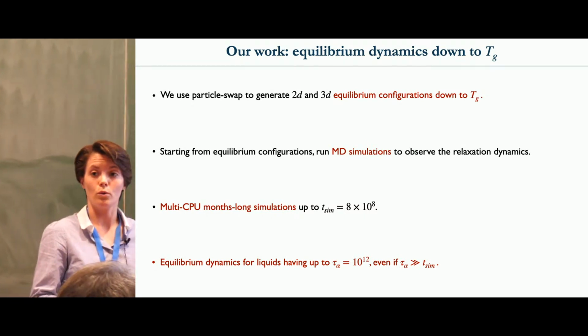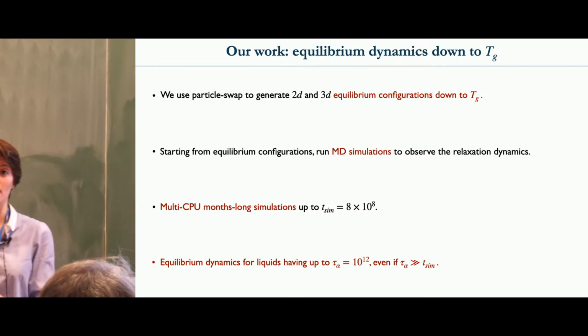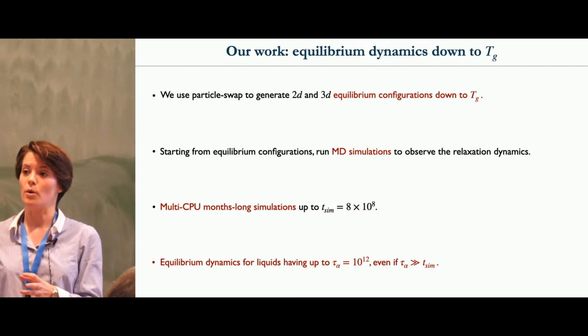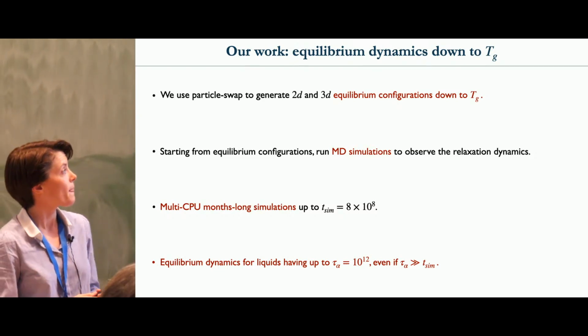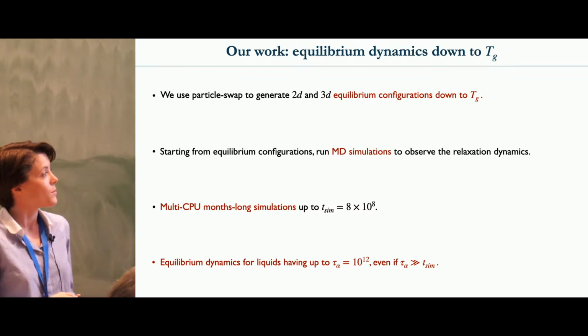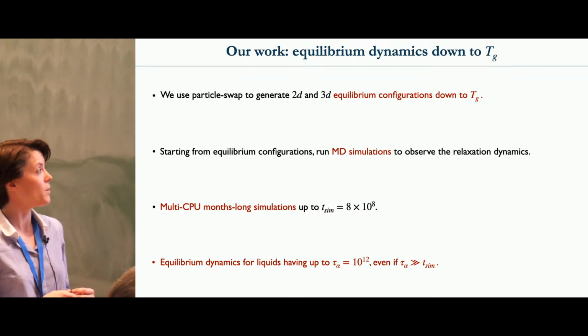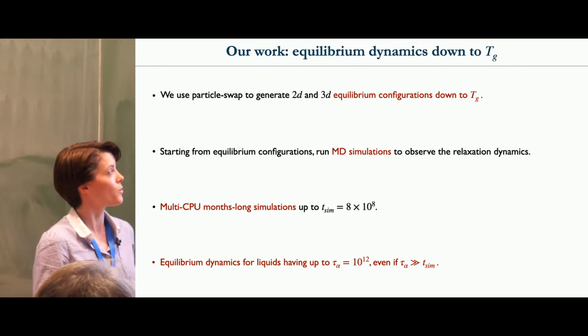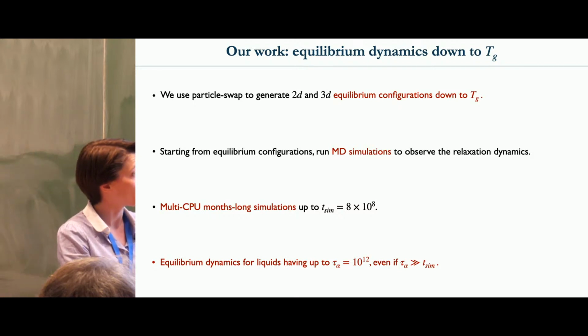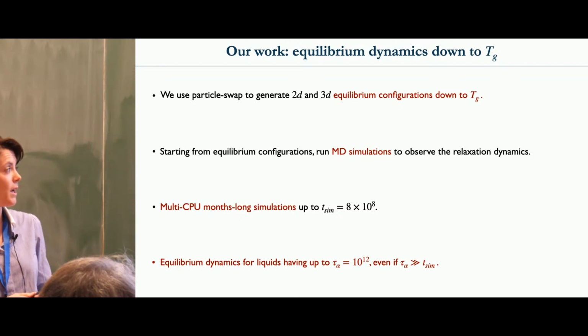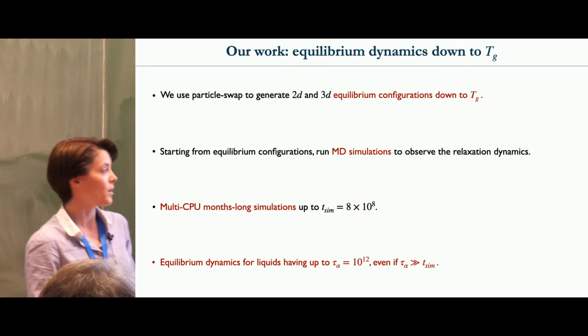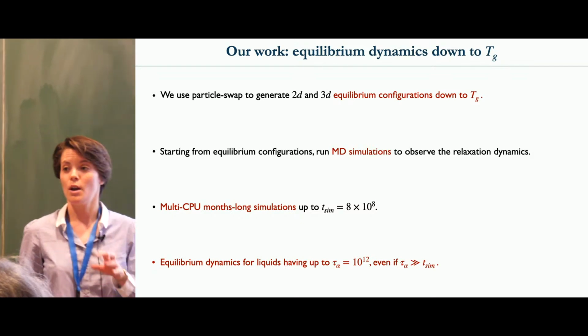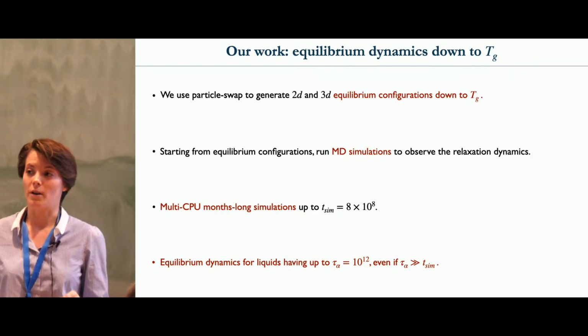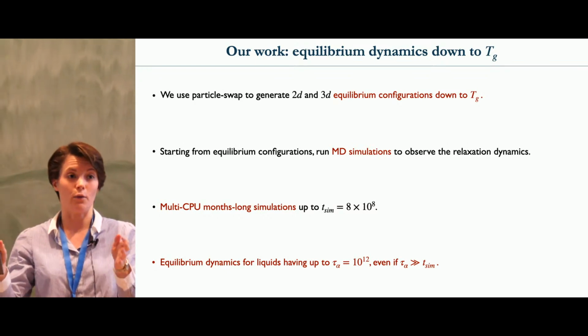So we use particle swap as a tool to generate equilibrium configurations. And then we take these as starting points for standard equilibrium molecular dynamics simulations, as everyone has done before. And we run the dynamics for as long as we can. So what I mean by as long as we can is really long simulations using many CPUs and also quite long simulation times. I will show you, for example, a 2 months simulation. So we're able to reach some really long simulation times, 10 to the 8, which is even a bit beyond the limit that I put before. And here the main point that I want to make is that even if the relaxation time is much longer than the simulation time, you can still run and observe the beginning of the relaxation, and this is actually really informative on the physics that's happening there.